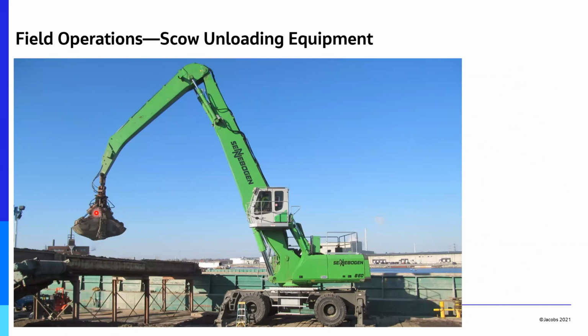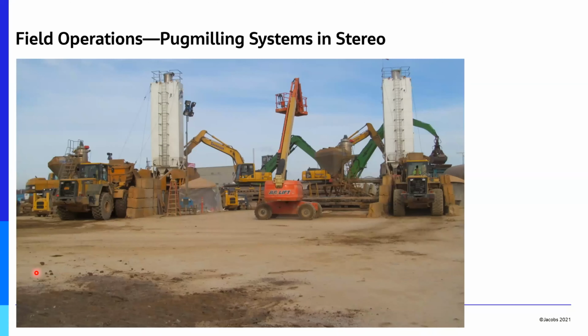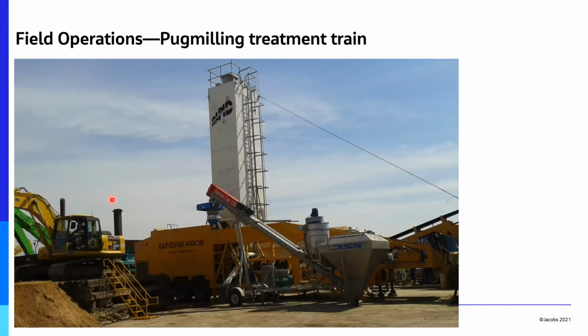So let's take a close-up of some of the equipment used here. This is a Sennebogen materials handler. This is what emptied the scow into our screening system and trash rack system before it went into the surge tank for the excavators, which are sitting here. They take the material out of the surge bin and drop it into the hopper for the pug mill. Here's your cement silo. The ferric sulfate came in on a different line. You can't see that here. And then these loaders took the material out.